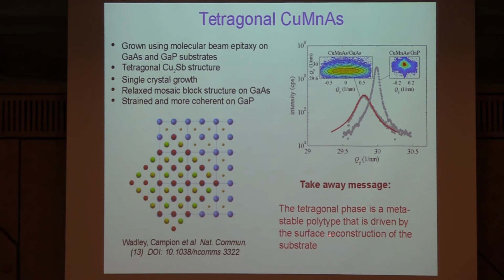The takeaway message from all of this, for anyone who wants to grow this stuff by sputtering or by MBE or by whatever other method, is that the tetragonal phase is a metastable polytype. Okay? It's not the ground state of the system. Okay? And it's driven by the surface reconstruction of the substrate. And that's really rather important, and it's worth remembering if you're going to have a go at growing this stuff. It's not the ground state of the system.